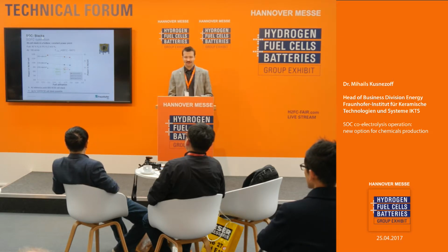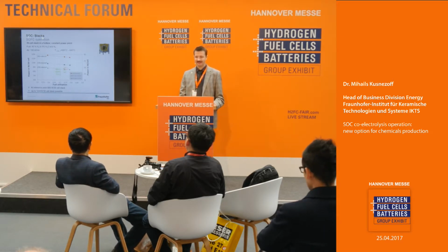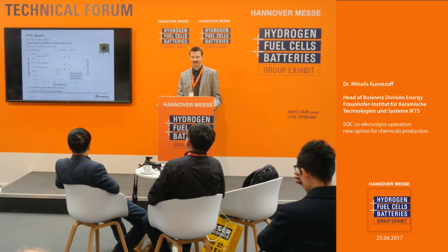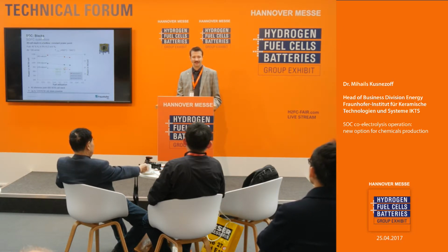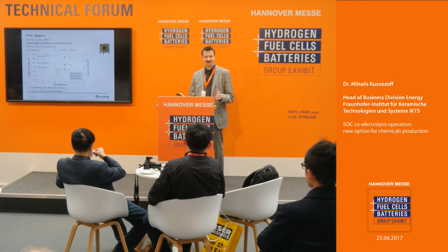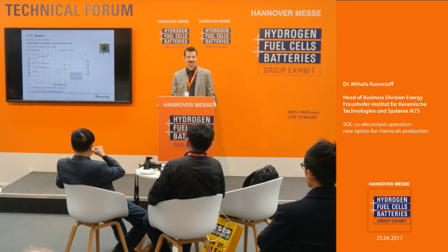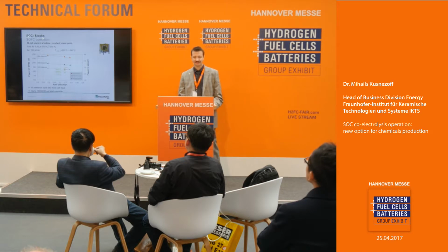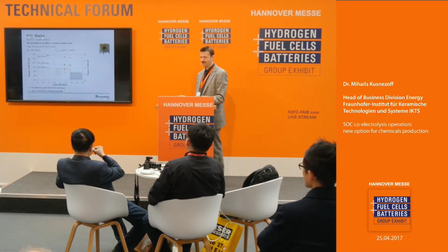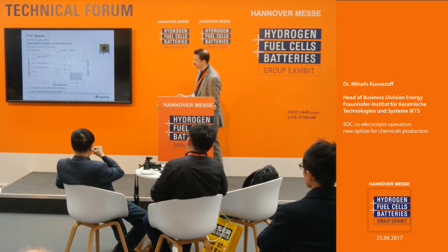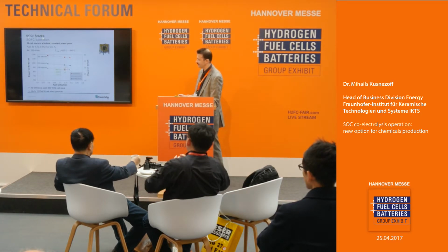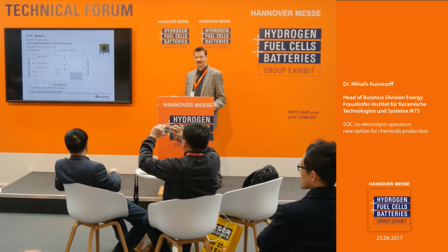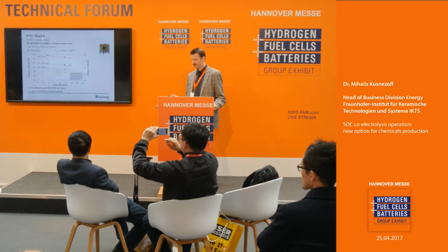If we look at the performance, then in SOFC mode we can operate our cells up to 30 watt per cell and achieve current densities of 400 milliamps per square centimeter, and delivering from a 30 cell stack the power range from 850 to something like 1.2 kilowatt.